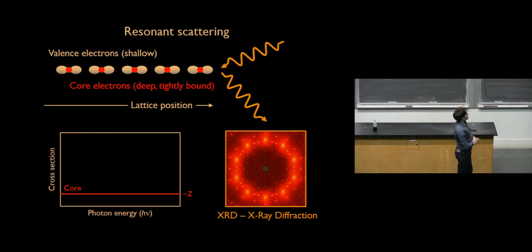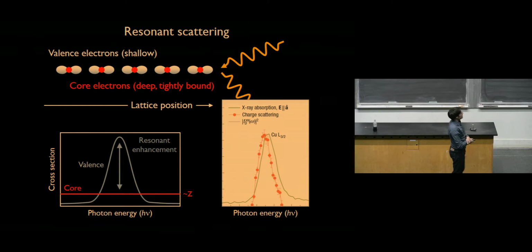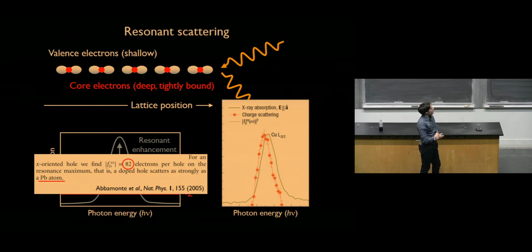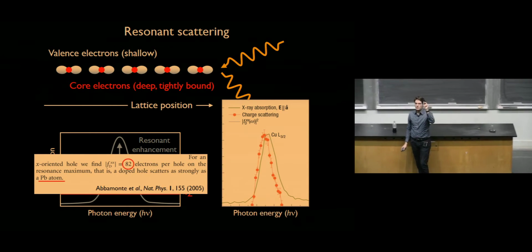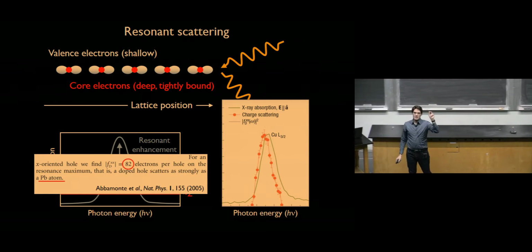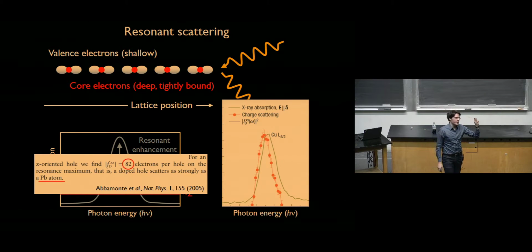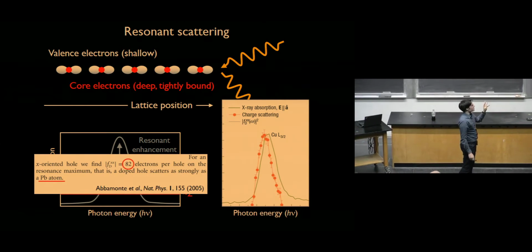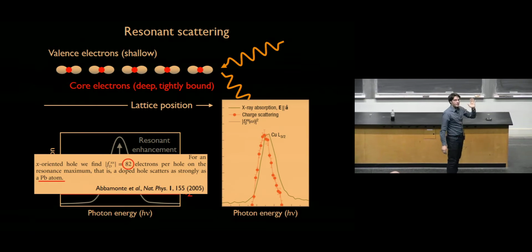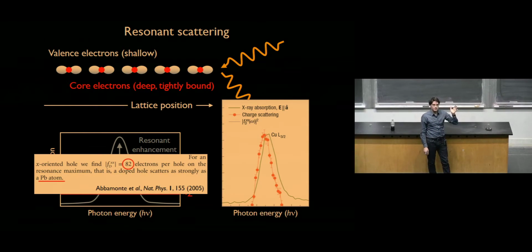So this is the photon energy dependence of scattering from the core electrons, or regular diffraction. It's pretty much constant versus photon energy. And when we do resonance scattering instead, we have a very strong enhancement at certain energies which correspond to the resonances in your material. And this is so strong that a single electron or a single hole in your material at resonance can scatter as strongly as 82 electrons, which is the scattering strength of a lead atom, which is a lot.